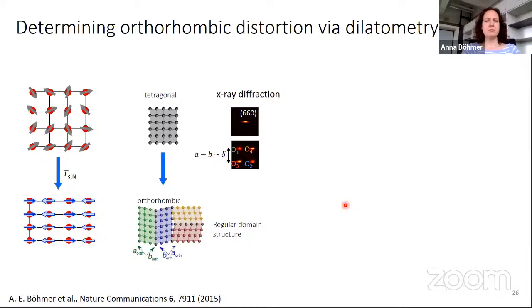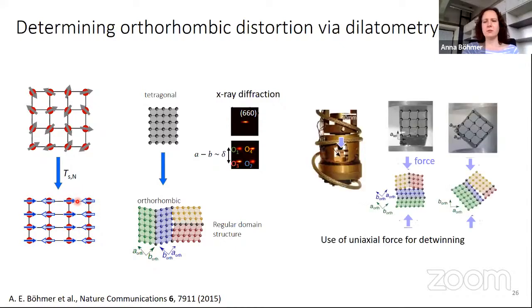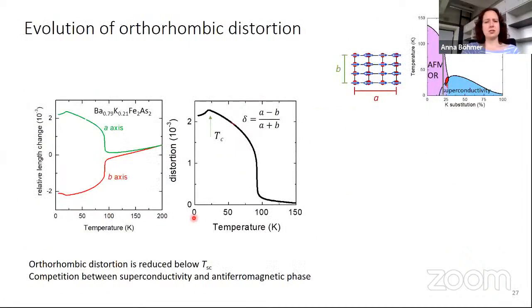One thing that we did is we measured the orthorhombic distortion using X-ray diffraction on one hand. That's what I already had. You see a set of peaks and the way they differ, that's how much your lattice differs from square, how much we go rectangular, how much we go into a magnetic state. You can also do that with length changes if you make sure you only measure this direction and not this. That's a short way. We did that. What we find is the orthorhombic distortion, the deviation from square, as a function of temperature, in a bit of the phase diagram here.